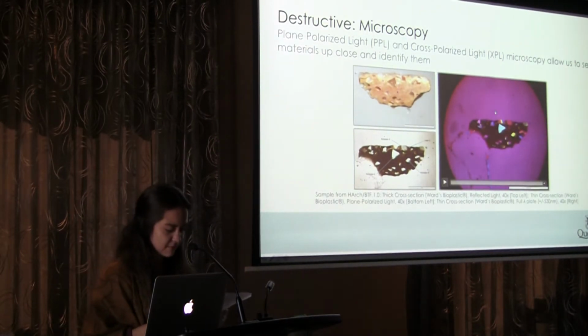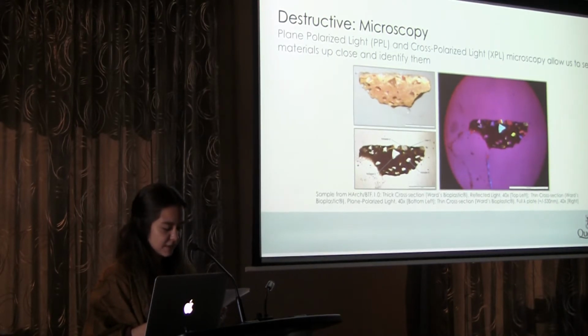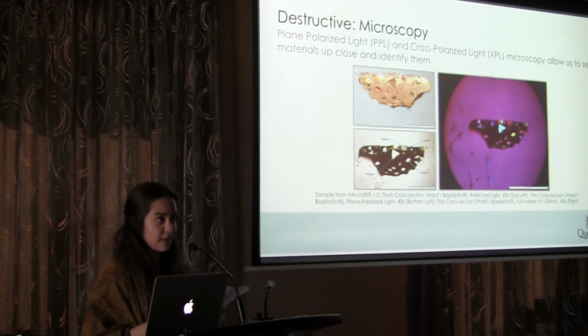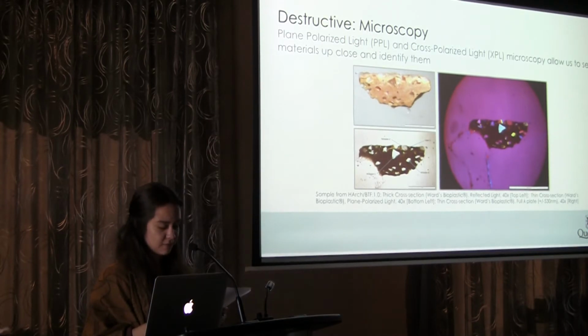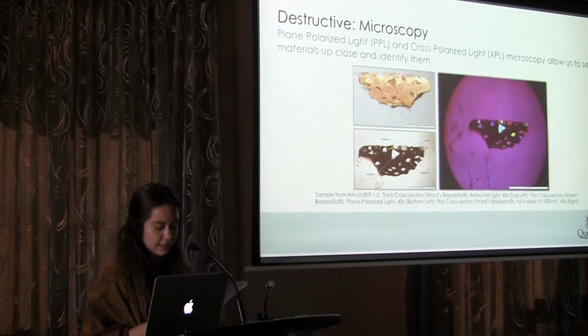In the case of ceramic vessel HARC BTF.1.0, examination of the sample under plane polarized and cross polarized light was able to tell us about the microstructure and composition of the materials used in its manufacture. For example, it was able to tell us that the inclusions seen are polymineralic. As you can see on the slide, they vary in interference and retardation colors.